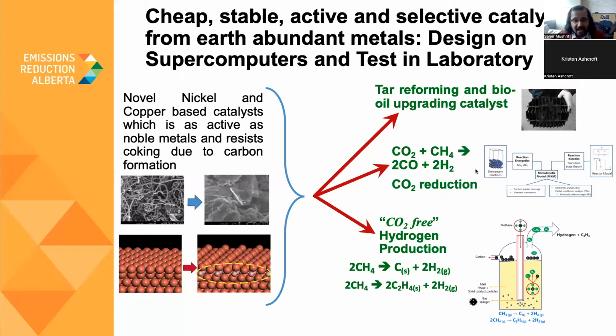And not only did we develop the catalyst in this piece of work, but we also simulated reaction-level kinetics at operating temperatures and pressure to test the performance of this catalyst under reaction conditions, which can be quite high temperatures for this kind of reaction. And last but not the least is the CO2-free hydrogen production. The reason I say it's CO2-free is you don't get carbon dioxide as a byproduct. But of course, if the energy that is needed to break methane to form hydrogen has a CO2 penalty, then you can't really call it CO2-free strictly. But if it comes from renewables, then you can call it CO2-free.